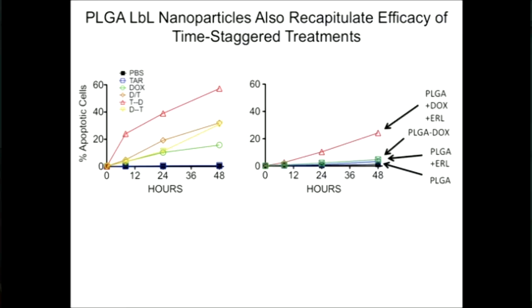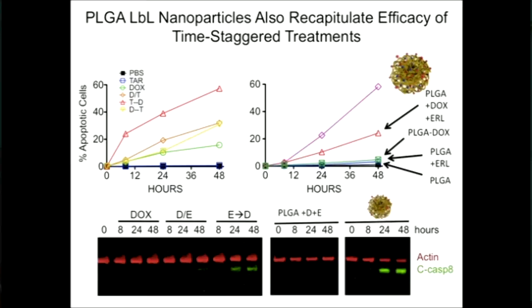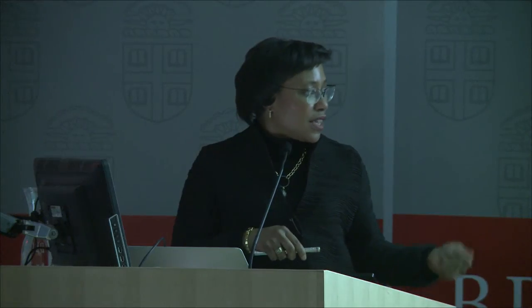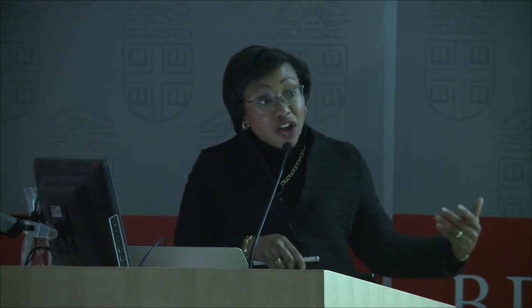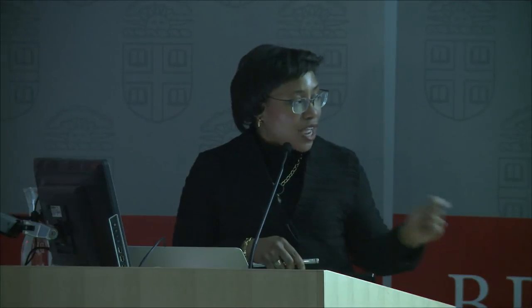So PLGA with just doxorubicin, versus the combination, versus our combined system, which gave us a much higher amount of cell death. There's a marker biologists use to indicate whether or not that pathway has changed. And the marker in this case was caspase 8, a protein that indicates one particular kind of cell death that's enabled when you have this sequence. And we found that we could replicate that; the marker is present in our combination system.